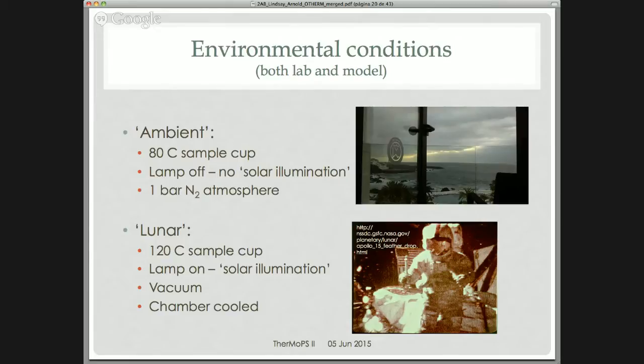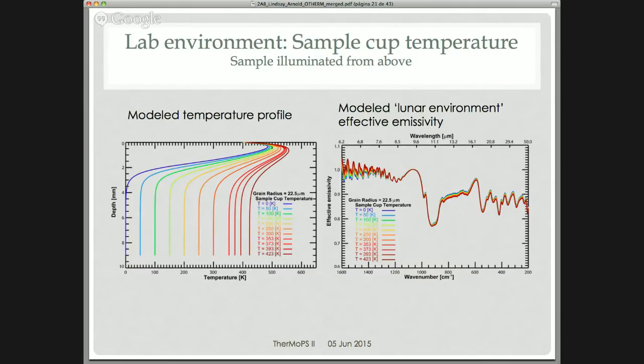So my first couple of plots will relate to how we actually make the thermal gradient in the lab. That's sample cup temperature and illumination, and comparing our model results to what we actually measure. So over here is our model temperature profile for different sample cup temperatures. Sean just showed something really similar, but that was for quartz, and this is for olivine.